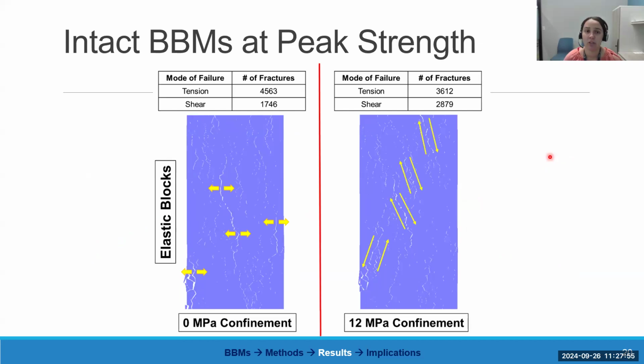And finally, I also want to show that we considered the micromechanical failure processes and failure modes of the model as well, in addition to these mechanical material attributes. So this is just the example of the elastic block BBM. We've got the 0 confinement, the UCS case on the left, and the highest confinement, the 12 megapascals confinement case on the right. So on the left, you'll see that this model has failed mostly through axially oriented tensile fractures. So this is akin to axial splitting and spalling, which we see in real life laboratory UCS tests of brittle rock. And I've also tracked the number of fractures failing in tension versus shear in the model. So you'll see that tensile fractures significantly dominate over shear fractures in this model.